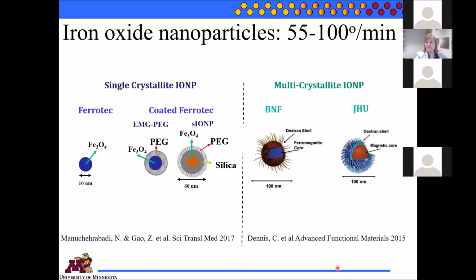Here are the particles that have been used to date. This is from that paper by my colleagues. This is Cindy Dennis and some work she's done with Rob Ivkov at Johns Hopkins University. So these are the particles, like this Johns Hopkins University particle is one designed by Rob Ivkov. These are what they're using right now to disperse in cryopreservation agents and then be able to warm and see how fast you can warm. And it turns out the fastest they've been able to warm is 55 degrees per minute, which is barely above that critical warming rate I mentioned of 50 degrees per minute. And with a high concentration, they can get to 100 degrees per minute.